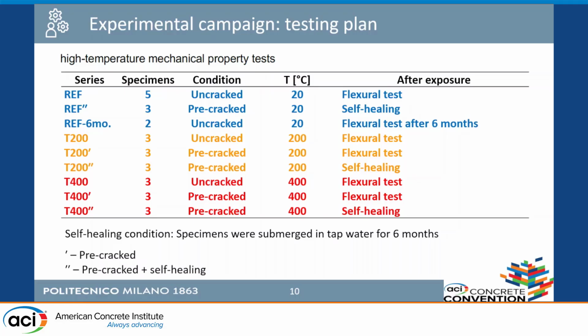It's important to say that the curing during the self-healing was underwater. This led to an overestimation of the self-healing. So if we had the chance to continue with this experimental campaign, the idea could be also to see what happened in other curing conditions. We stopped at 400 degrees C.